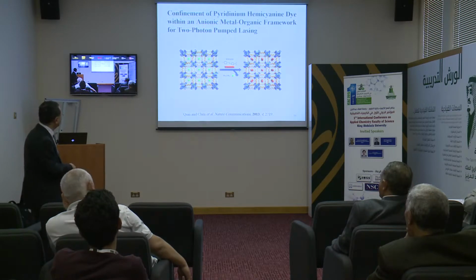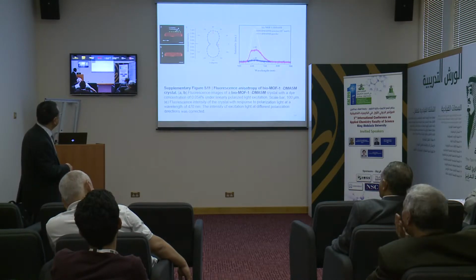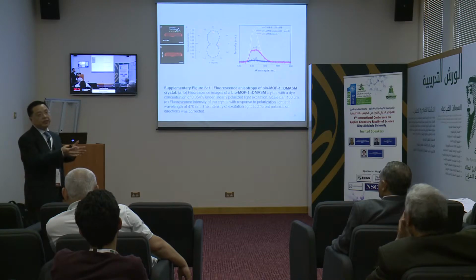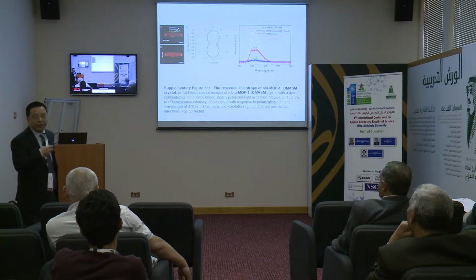So here we can exchange, and we see under dilute conditions, these molecules are oriented. And this orientation and pore confinement significantly diminish the quenching effect. As we know, this is easily quenched in the solution or in the solid state. So the luminescence property is significantly higher than those in the solution and the powder. So this enhancement is a potential application for lasing.